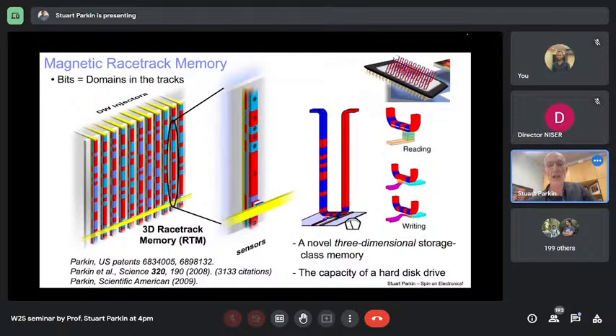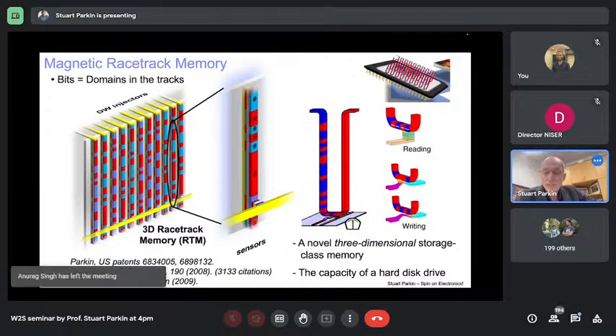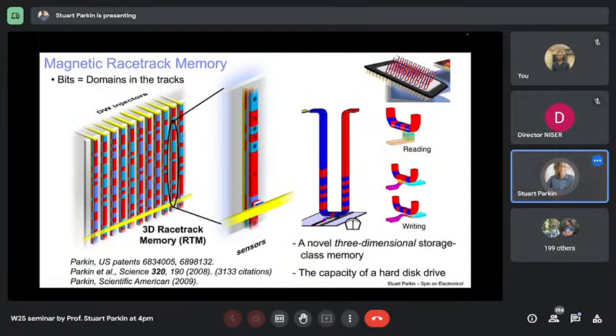And again, this is a very old cartoon that I first prepared with the help of Kevin Rush many years ago. And this was my concept, that we would build a device that is innately 3-dimensional. Build tall, vertical, magnetic nanowires. And in these nanowires, we would magnetize the wires in these blue and red regions, magnetization pointing in opposite directions. And the information is encoded in the walls, the domain walls between red and blue regions.